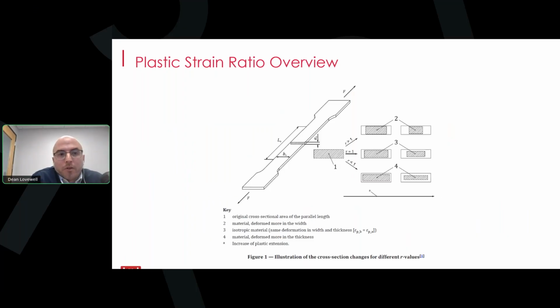So this diagram from ISO 10113 shows the profile of a strain specimen in tension for different R values. On the top, specimen number 2, we see the effect of an R value greater than 1. So this material would be resistant to thinning. As it's stretched, it would tend to spread more outward in the width rather than get thinner. So this material has good drawability and would be a good fit for a part that required forming into complex shapes or where a lot of strain hardening was desired.